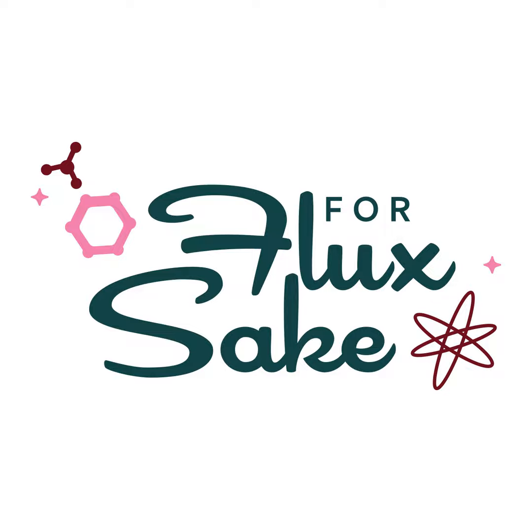But this is where those silicon carbide shelves become a bit of a problem, because the silicon carbide, when fluxed with a little bit of sodium, will turn into a glass and they will stick together. And that's where the plucking happens, because they're fused together just a little bit. And when you pull that pot off, if there's a weakness in the clay, that clay will break to relieve that stress. And that's where you get those little plucks hanging around.